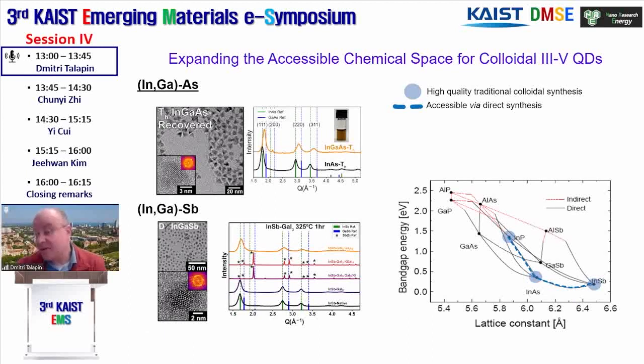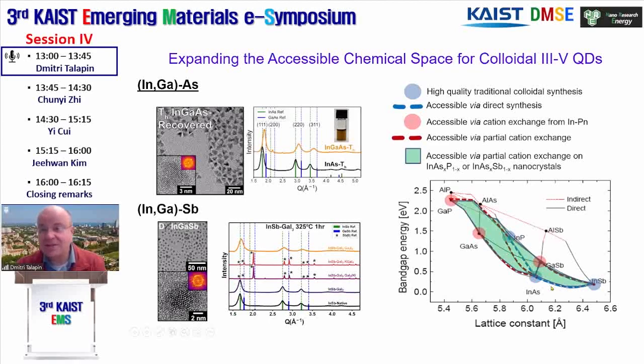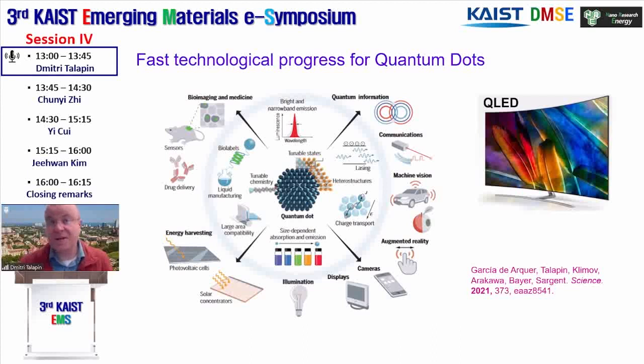But judged by several decades of hard work using organic solvents, I strongly believe, and our most recent data show, that you need molten salts to make these other compositions. We have demonstrated the possibility of making these materials, and all this space can be covered using molten salt synthesis. So I have many reasons to believe, and many experimental data to justify these claims, that molten salts open up a much broader space for colloidal synthesis. And altogether, it helps us to further advance technological progress for quantum dots as a field.